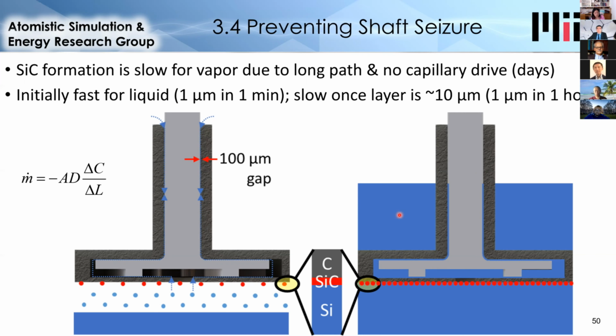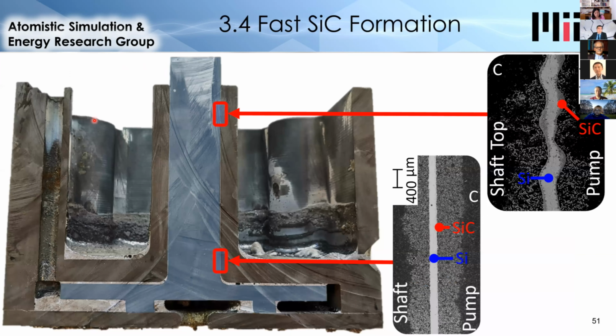So at least one method is to lower the pump slowly so that while the reaction happens quickly locally, at least the entire surface isn't reacting at the same time. And this means that if any silicon carbide bridges the gap between the solid and the dynamic component, at least those few bonds can be broken before more of them form. And this technique worked, except that in the first experiment, the pump wasn't lowered far enough into the silicon, but this actually gave us a very interesting insight into the mechanisms going on.